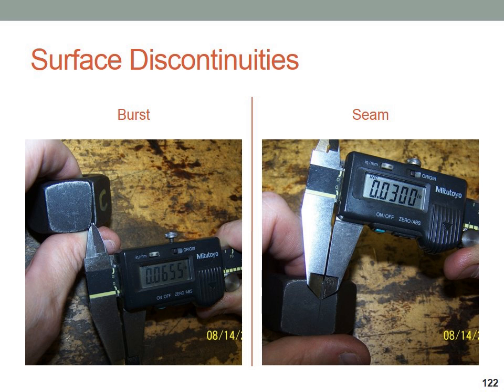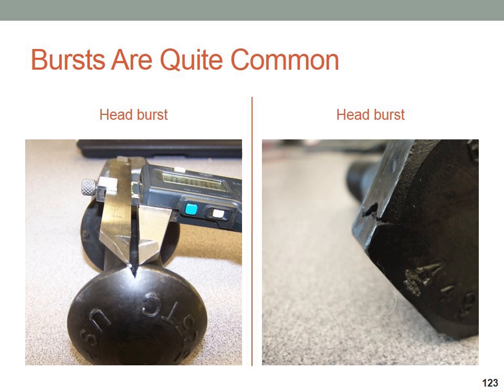We have permissible limits for these established within ASTM on what's a permissible and non-permissible amount of burst. But it can make people uncomfortable when they see it, even though it may not affect the performance at all. There is a difference between a burst and a seam, although sometimes seams split open and turn into bursts. We see them occasionally on nuts. We see them more frequently on bolts. We do tend to see them more on round-headed or twist-off type bolts than we would on hex-headed bolts, simply because a good portion of a hex-head bolt is actually trimmed off as one of the last operations, so a lot of those bursts may have existed and then been trimmed off.